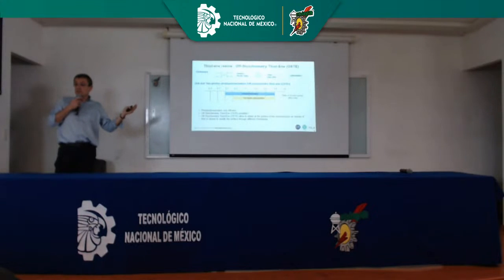What is nice, you can control the ratio of these two components. So you can adjust this. Why? Because by adjusting it, you can adjust some mechanical properties of your polymer once it's polymerized. And also, you can end up with an excess of thiol in your resin or an excess of alkene, which means that you are able to modify the surface of the microstructure. So we have performed many trials in order to characterize our system, and what we have seen is that we are able to photopolymerize with ratios ranging from 2:1 to 1:4, making our system very flexible in terms of mechanical properties, as well as in terms of possibilities to graft molecules on the surface.